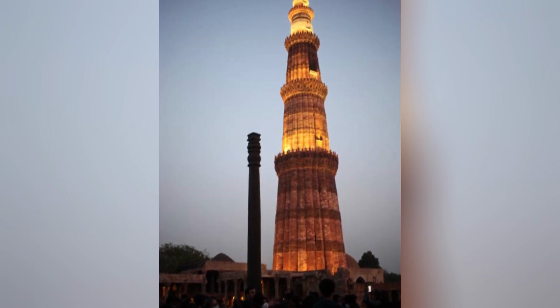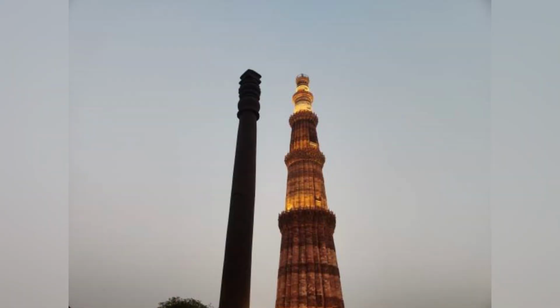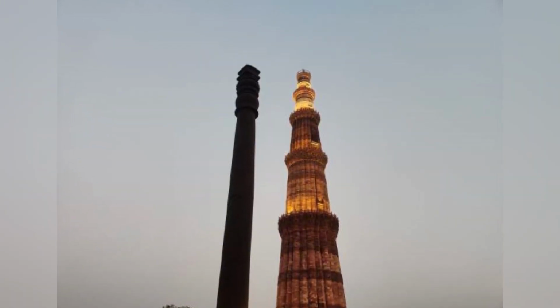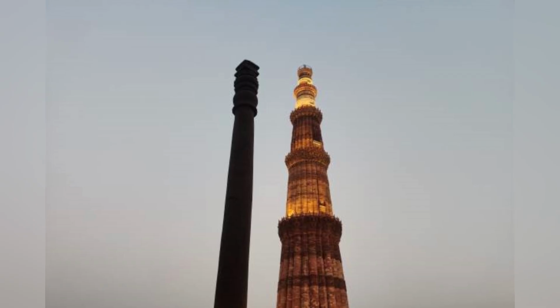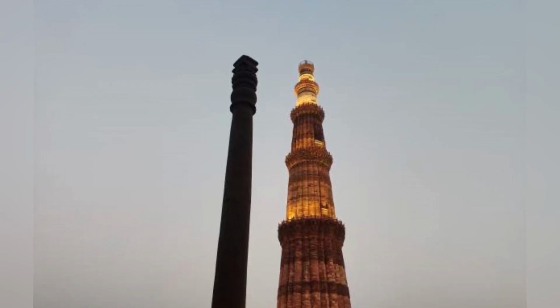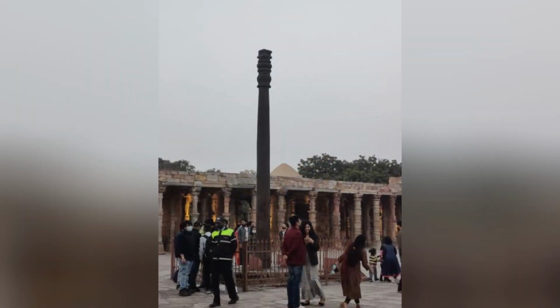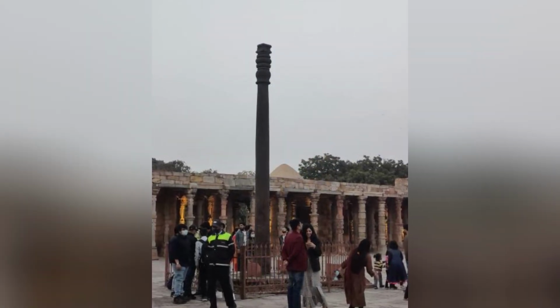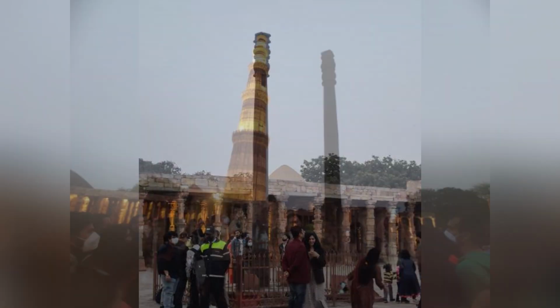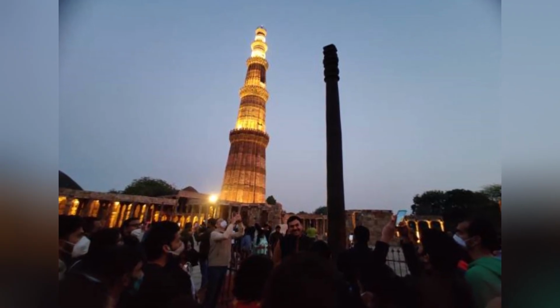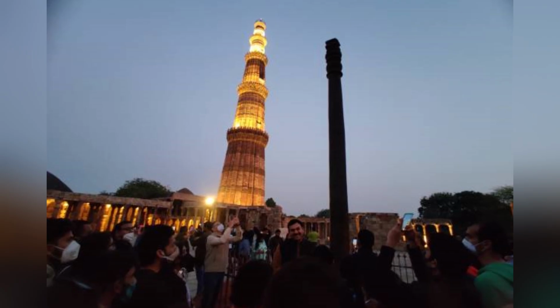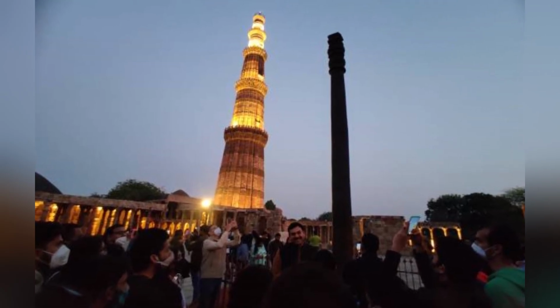The mechanism by which the cyclic wet-dry exposure promotes the formation of the protective film has been elucidated by Balasubramaniam through a combination of field observations and laboratory experiments. During the wet season, moisture condenses on the surface of the pillar, dissolving the iron and the phosphorus at the surface, and creating a thin layer of electrolyte in which the electrochemical reactions that form the film can occur. The phosphorus in the iron reacts with the iron ions and the water to form iron hydrogen phosphate hydrate, which precipitates on the surface as a thin layer of the protective compound.